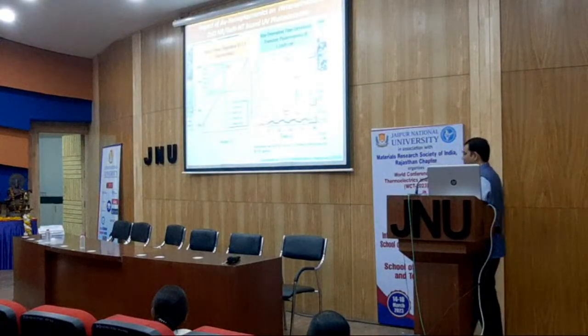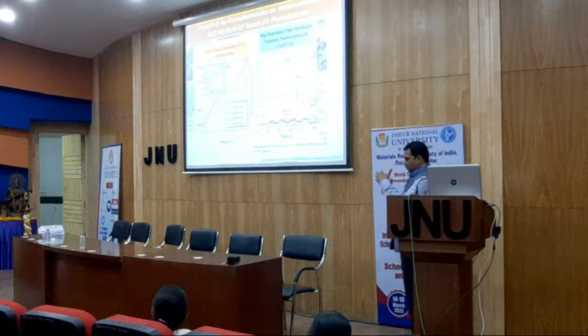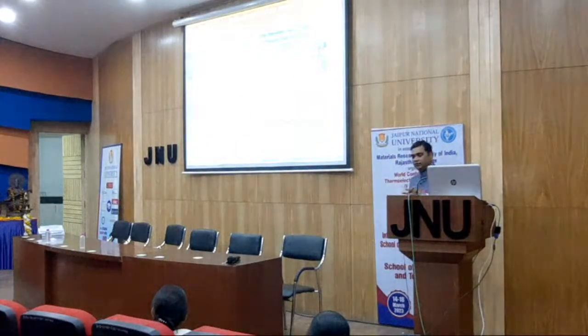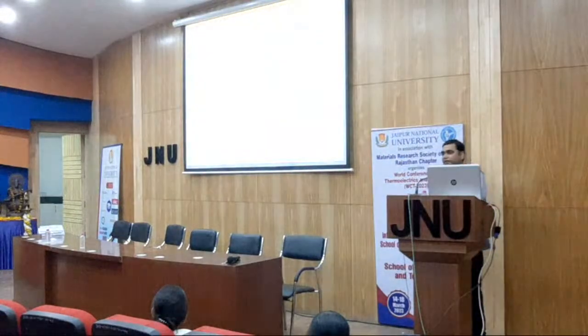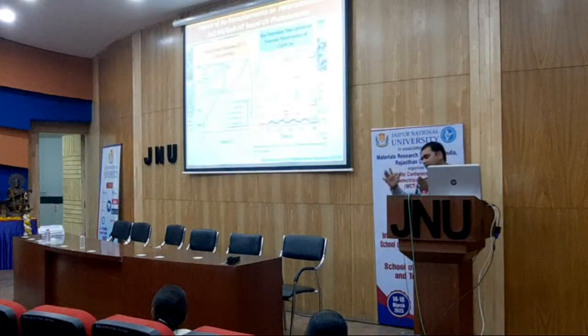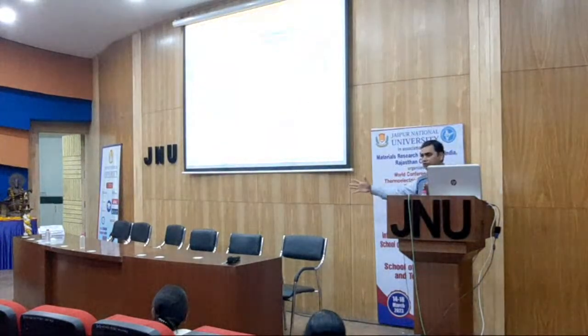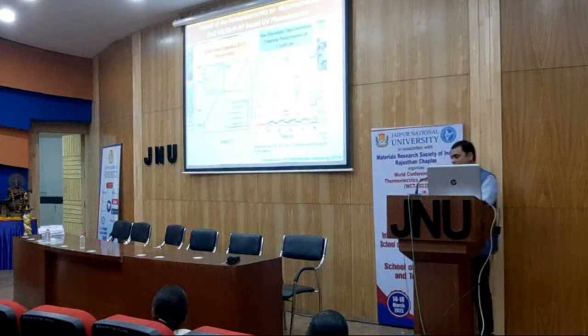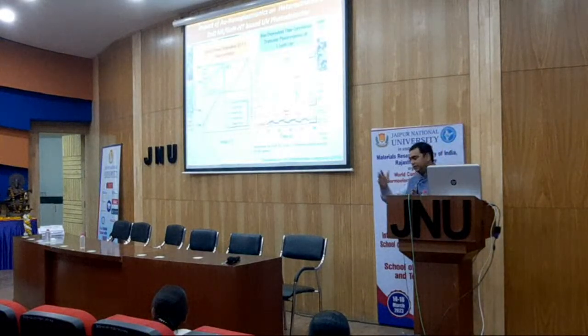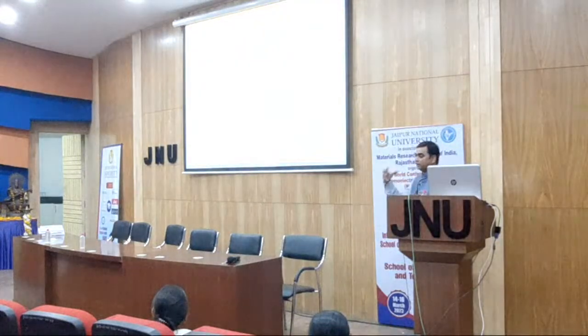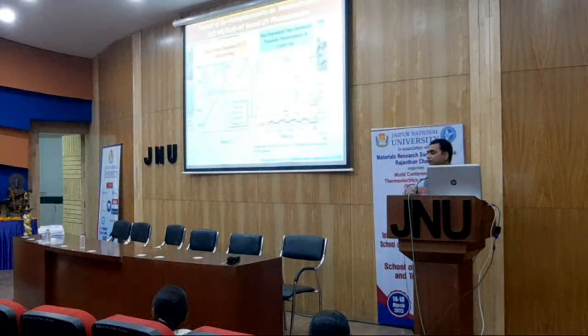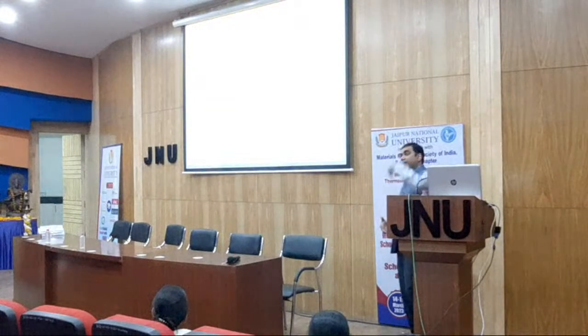Now, when we are talking about gallium nitride, then on top of it zinc oxide, on top of it gold nanoplasmonics, we are generating a number of interfaces. When we are talking about interfaces, the transport of charge carriers is very poor, I would say, because you have to cross the hurdle. One hurdle is there, then a second hurdle is there. But because of the structure, light-matter interaction, you are generating more photons. So photocurrent is higher. But since there is a hurdle, the response time is delayed.